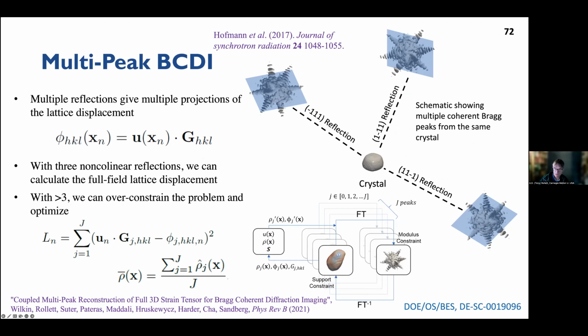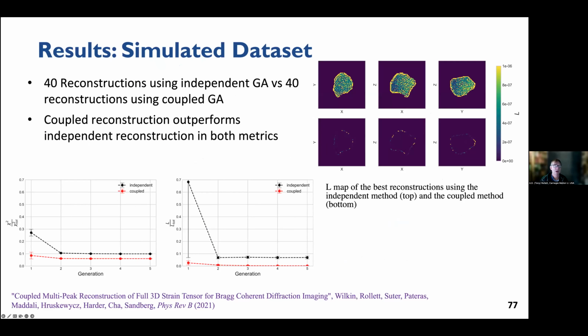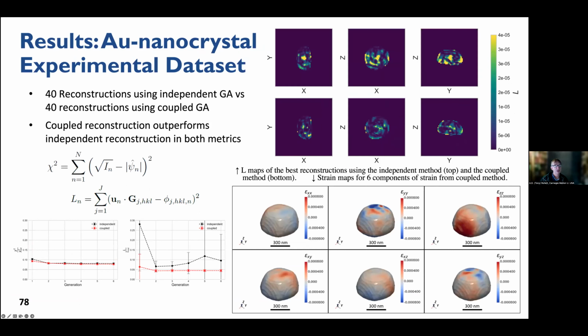And from that, we have been reconstructing both made up data sets, simulated data sets, but also actual experimental data sets. So that's a simulated data set. What I'm showing you here is contrasting what you see in the error measure. If you do the traditional independent reconstruction, that's the sort of error signal you see. With the coupled approach, you can significantly bring down the errors, and you don't have quite such a tendency for that error to be large near the edge of the crystal, which becomes very important if you want to actually look at defects close to interfaces.